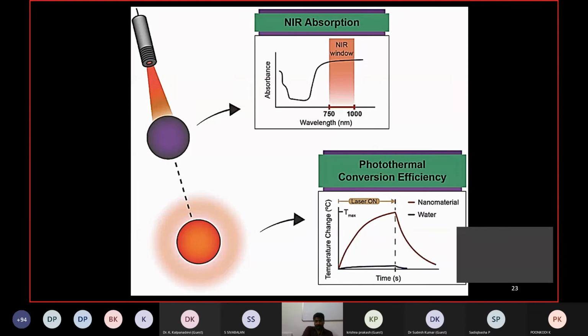Okay, look at that. This is the photothermal conversion efficiency measured as a function of time. The temperature changes. The material absorbs radiation and gets heated. The heat increases up to a certain time, and it becomes constant, and then it falls down. When the laser is on, the material absorbs and shows a heat change. So the heating efficiency may vary for different materials. It could be up to even 73 degrees.